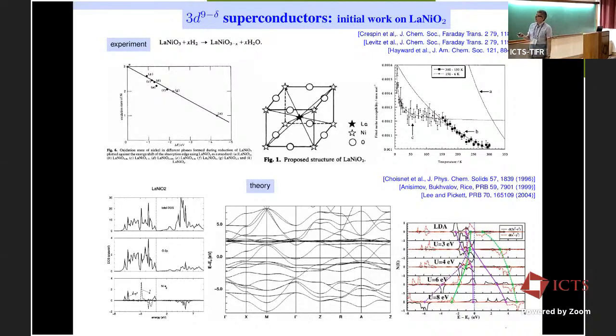Then continuing calculation by Anisimov's group from Russia, Ekaterinburg, and also from Warren Pickett's group in the US, made that more clear. It has an x² minus y² like dispersion, that you can see here. But there are some additional bands touching the Fermi level, this kind of self-doping pocket bands, which maybe complicates the picture different from cuprate again, where you don't have those states.